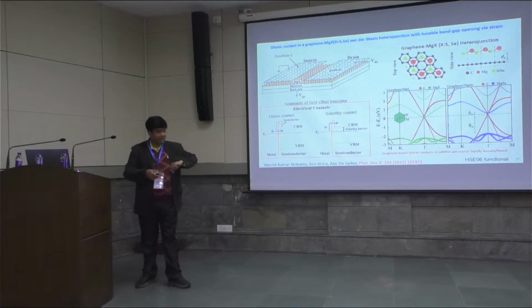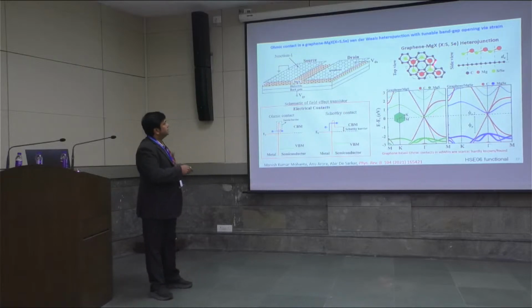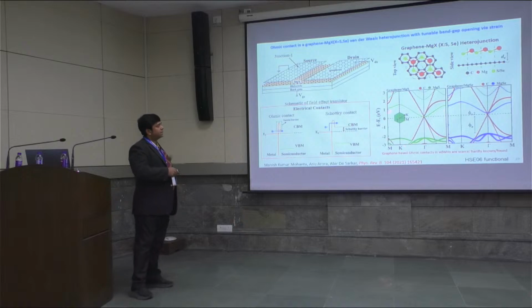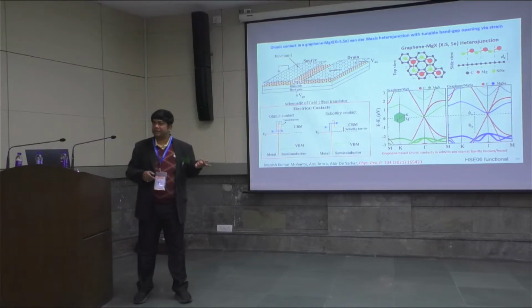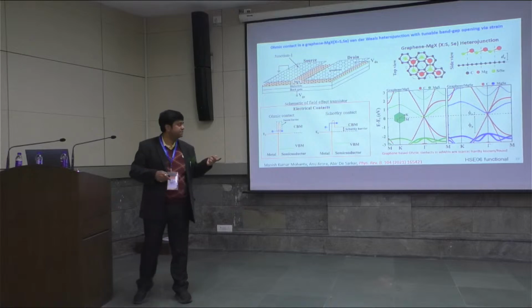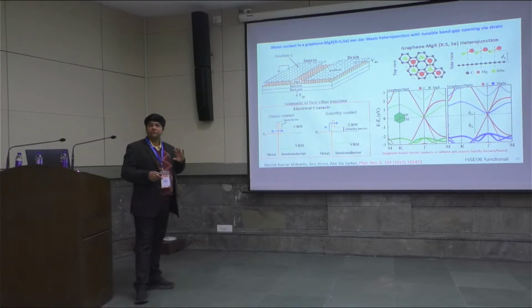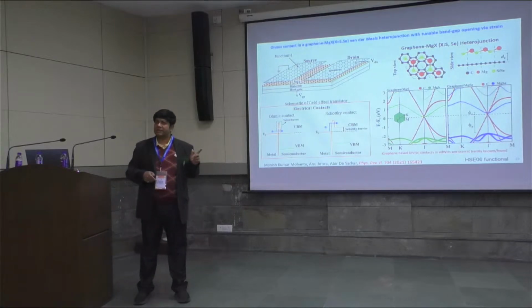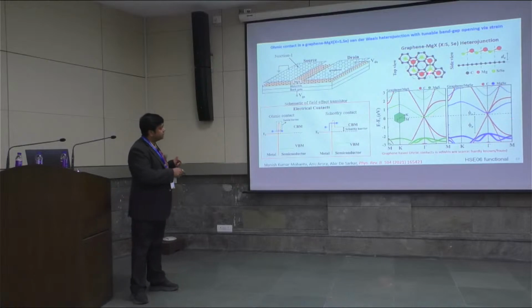Yes, please. So as I mentioned, serendipitously we have come across an ohmic contact in this van der Waals heterobilayer. The materials that we study are finally utilized in devices, therefore it is very important to understand the device properties. The occurrence of ohmic contacts is rare and uncommon, and serendipitously we have found it in this van der Waals heterobilayer when MgS is stacked on top of graphene. That means the Schottky barrier is 0.